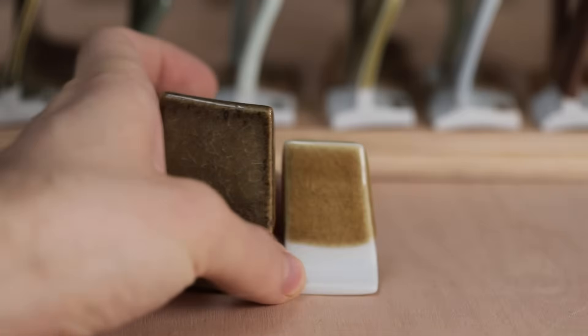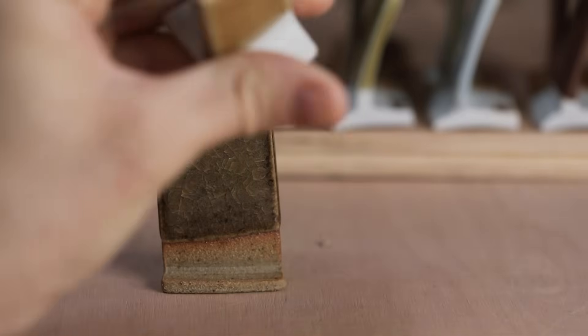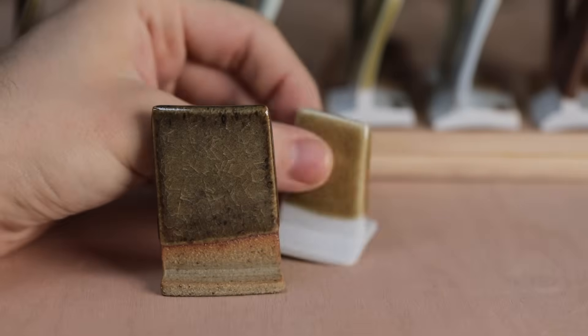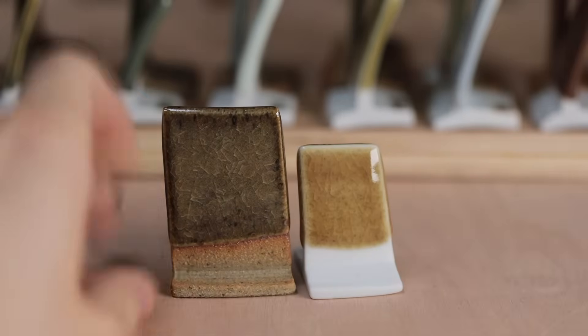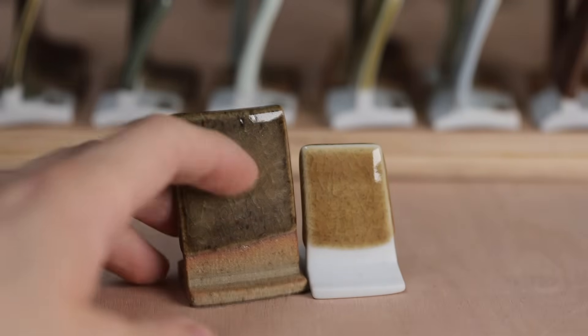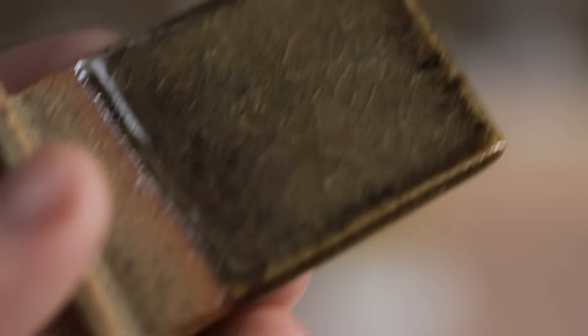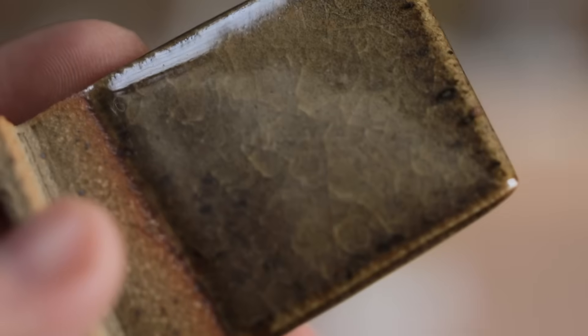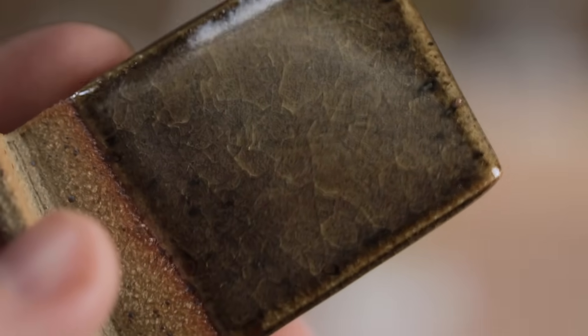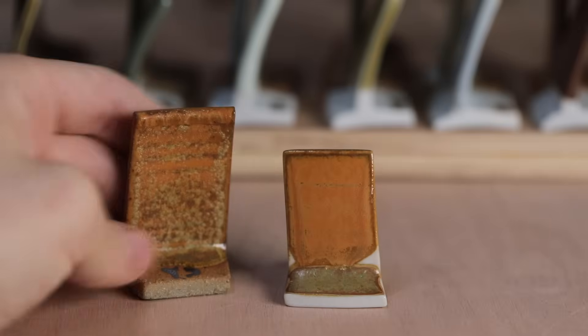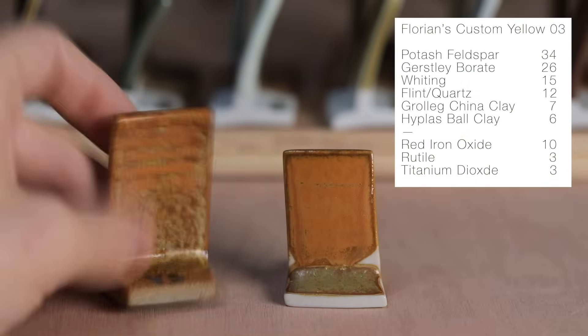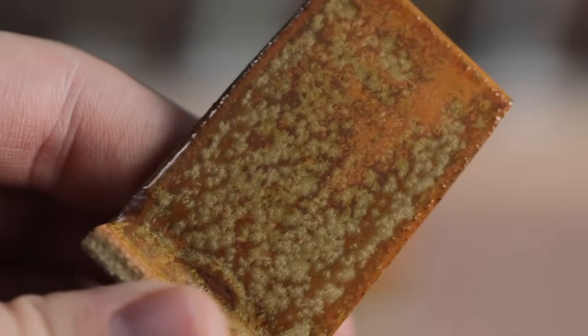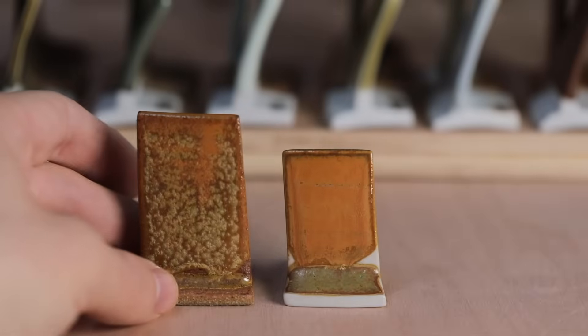This is another version of my base crackle glaze, but with the same addition of colourants as the previous tests, so titanium and red iron. And whilst I do like what it does on the edges, where the darker black border begins to appear, overall it's just far too brown for me. Brown pots aren't something I really want to make, but it was a good test to do nonetheless, as even a failed test still provides you with a wealth of information. Here's another test which, colour-wise, is rather amazing, and the stoneware version also has these crystals that grow, but it was far too fluid, due to the insane amount of red iron oxide and rutile it contains.